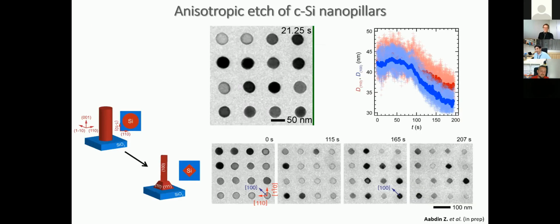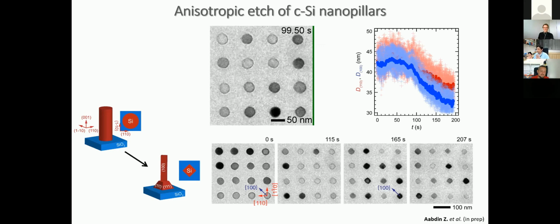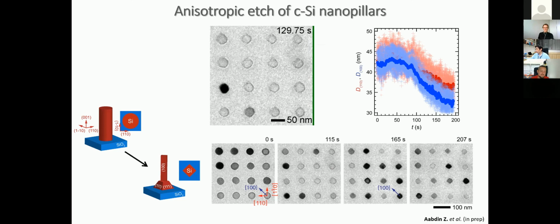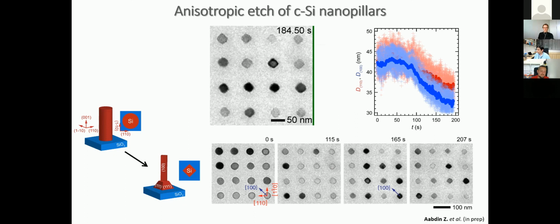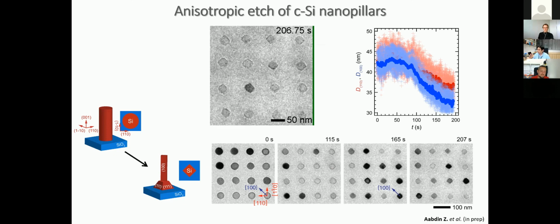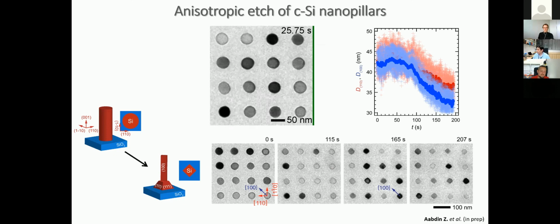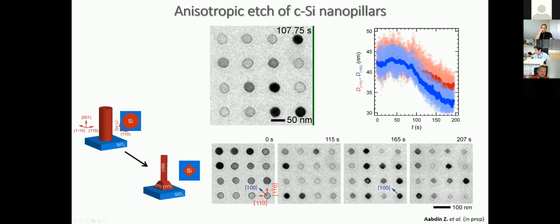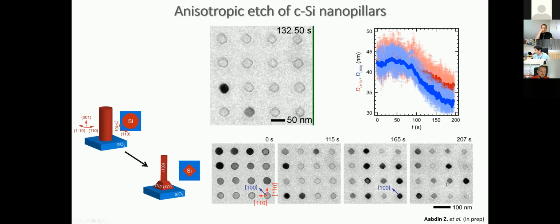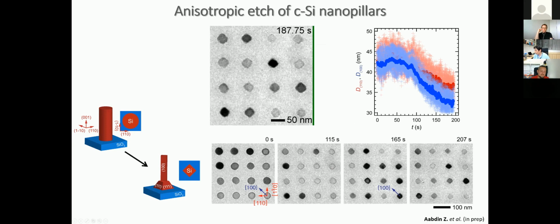Okay, so this is the movie, and then you see this flickering. The flickering is just because the membrane is not very stable, so it's like its own axis, like silicon tilting. But you see how this etch is happening, right? So you see etching. Now since it's crystalline, you clearly see the anisotropic etching. Certain fast etch directions etch faster, and the slow etch directions, the planes, don't etch, and you end up with this kind of a diamond shape pattern, right?